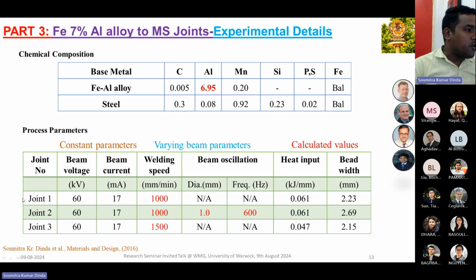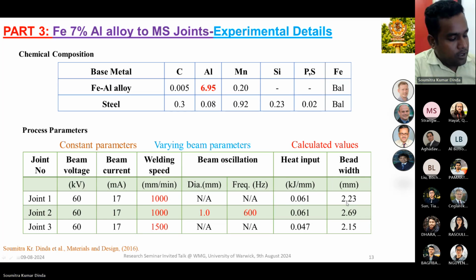The good thing is that if we compare joint 1 and joint 2, the welding speed is fixed, but in joint 2 we are using an oscillating beam of 1 millimeter diameter at 600 hertz frequency. If we compare joint 1 and joint 3, we are changing the welding speed, but in both cases we did not use beam oscillation. We calculate the heat input as voltage times current divided by welding speed, and we can see the heat input is quite low, 0.061 kilojoule per millimeter. And the weld width we calculated after taking the sample out of the chamber.